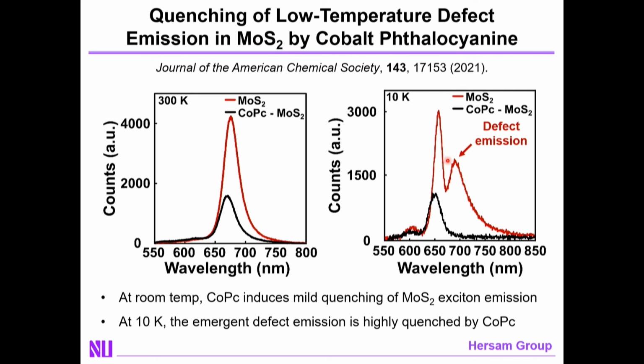However, when you go to low temperature, what you observe is that there's a secondary peak that emerges. This is often referred to as a defect emission peak. This peak is quite problematic in many contexts, including in quantum information sciences, because these defect peaks will complicate the interpretation of single photon emission spectra from transition metal dichalcogenides. So the question is, can we do something about this defect emission?